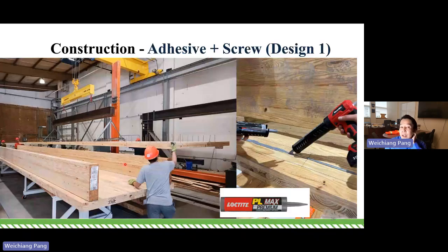So this picture shows the construction sequence. For the adhesive plus screw, we pre-drill all the screws, embedding them to almost the thickness of the CLT panel, and then we stop. Then we put the adhesive on the glulam, right? Because we only have limited working time before the adhesive starts to set, so we need to drive all the screws into the CLT panel.